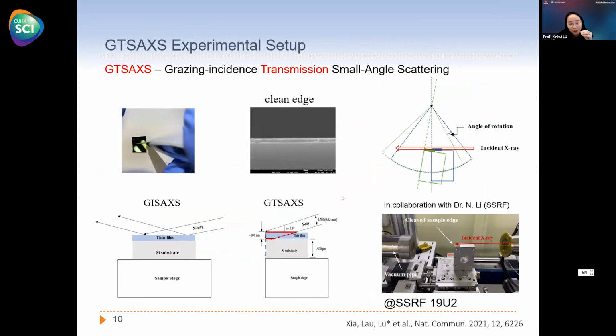So to get such a signal, called the GTSAXS signal, we have to cut our sample at the center, make a clean edge like we create for the cross-sectional SEM measurement, and then we place our sample at the center of the rotational stage, and shine our incident X-ray at the front edge. So in the conventional setup, the X-ray is shone at the center of the film, so the X-ray signal cannot escape from the substrate, because the substrate is very thick. But if we shine this X-ray at the front edge, then the pathway for the scattered X-ray can escape from the front edge, and then we can get the below-horizon signal.